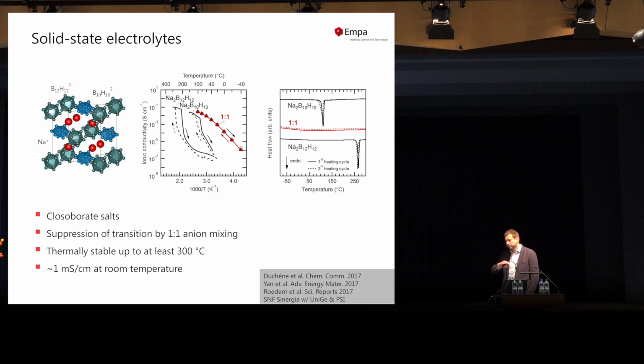But we were able, by mixing these two anions into this FCC lattice, to completely suppress this transition. And this happens exactly at a ratio of 1:1, and that's for a specific reason. We were able to stabilize the high symmetry phase of these materials already at room temperature. What you see here is simply the extension of the Arrhenius behavior of the high symmetry phase. So we now have a solid-state electrolyte with an ionic conductivity of about 1 millisiemens per centimeter at room temperature. So this enables us to develop a battery.